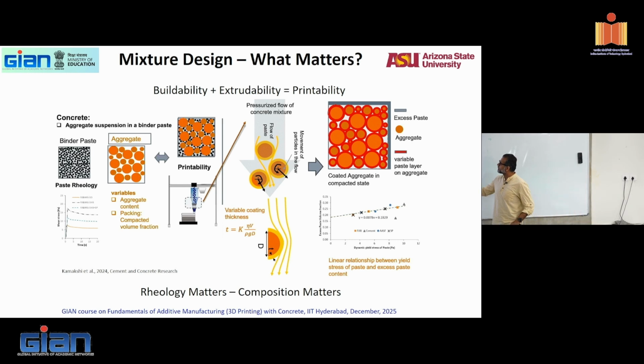Now, to get a good yield stress and plastic viscosity that you want to flow, you want a certain amount of paste coating the aggregates, right? And that's what you heard in the morning. Your codes will do all of that empirically. By specifying the minimum cement content for workability and a minimum or maximum water cement ratio, they are simply specifying a certain paste volume. And depending on your aggregate sizes, you can find out based on surface area what is the thickness of the paste.